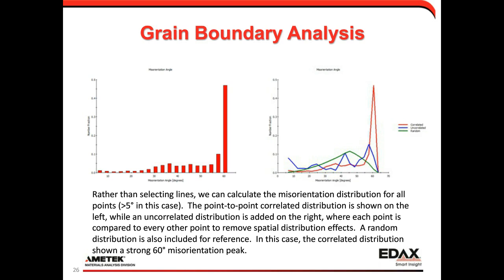And what we see is that relative to the random distribution, there are certain peaks that are occurring in the correlated and uncorrelated distribution, which give us an idea that specific grain boundaries are developing within the microstructure. And again, one of those peaks is near that 60 degrees.